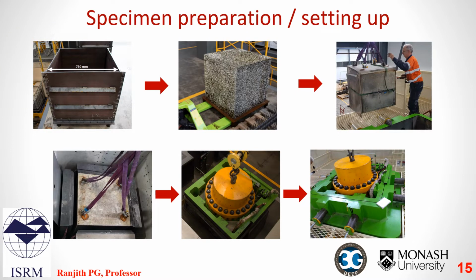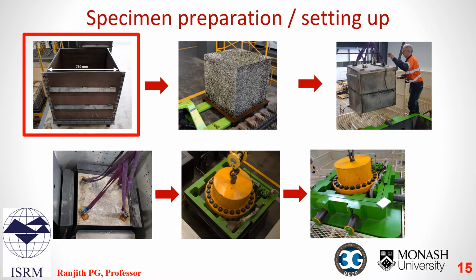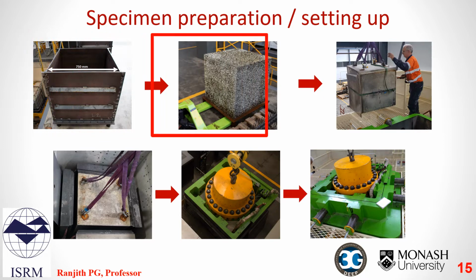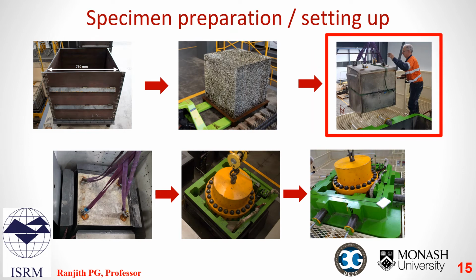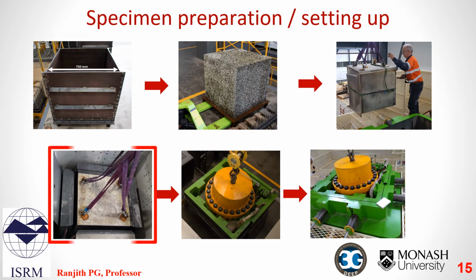Now, having an idea of the different components of the stress reactor, let's look at the specimen preparations and loading procedures. For commissioning the setup, we have produced a large 750 mm cubic mold and casted concrete blocks for testing. These blocks are placed in the reaction chamber using a 12-ton gantry crane sitting above the test setup. We move the blocks by drilling anchor bolts into the specimen to allow hoisting.